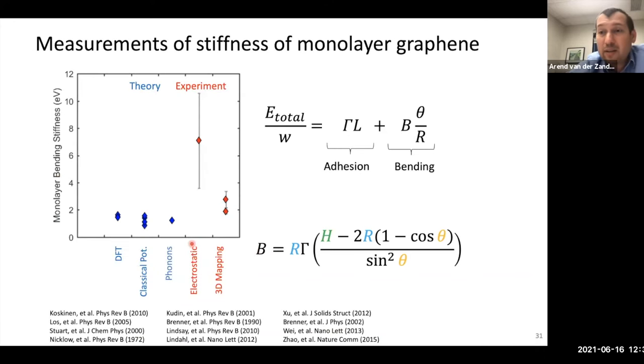So the first thing we wanted to know is, what is the stiffness of a single layer of atoms? If you go back in the literature, again, people have been trying for a while, but if you look at the values that people get from theory, they predict values that are quite small. But then when people try to measure experiments, look at the error bars on this. First, it's quite big. Second, error bars are ridiculous. It could be anything.